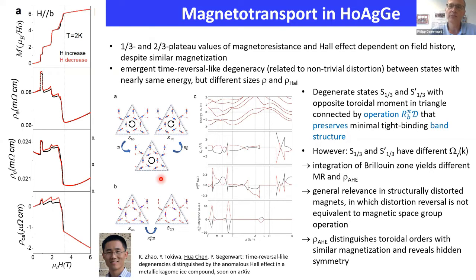And so he did a calculation where he just assumed a minimal tight binding model, a minimal tight binding structure with s electrons on the positions of the holmium sites, and found that indeed these two configurations have a similar band structure, but their Berry curvature is distinctly different, not just having opposite sign for the two different configurations, but with different absolute values. And integration of that then leads to different so-called orbital magnetization and different anomalous Hall effect, as indicated here over the Brillouin zone, and that could explain this difference which we see in this time reversal-like degenerate state in the magnetization, this difference here in the magnetotransport data.